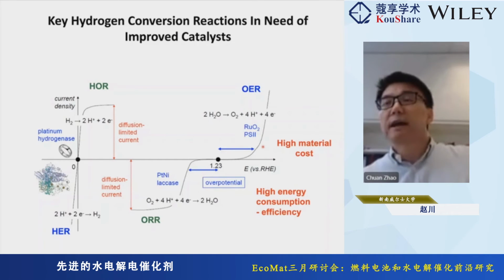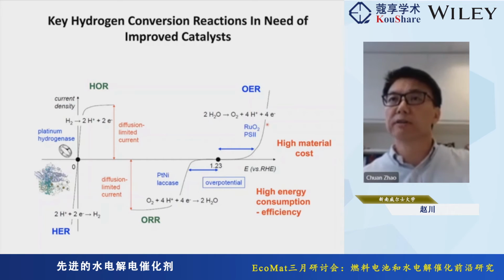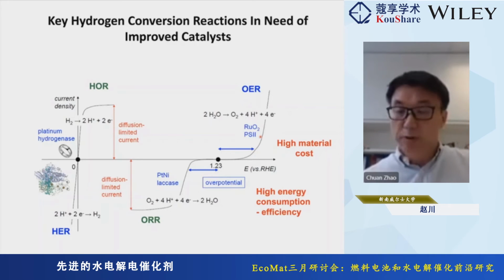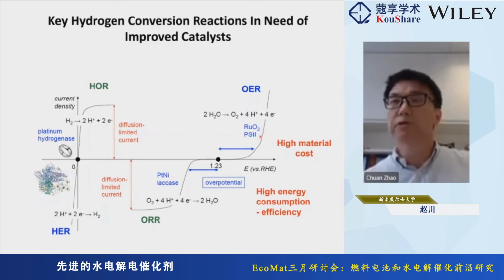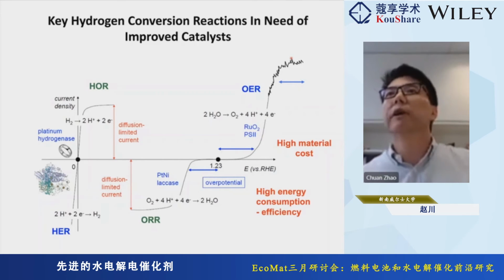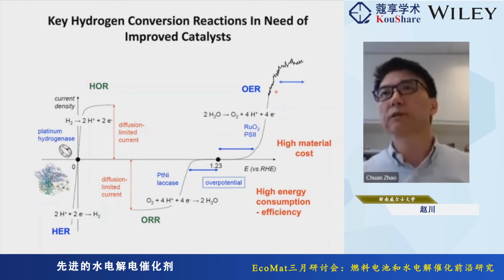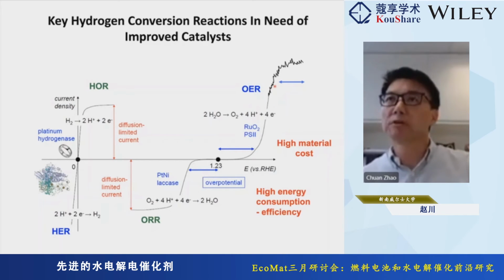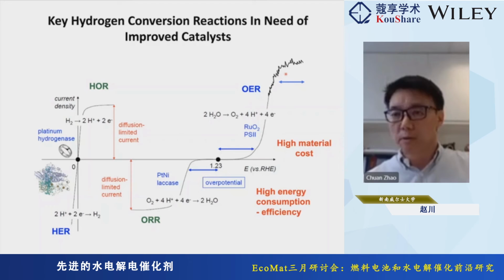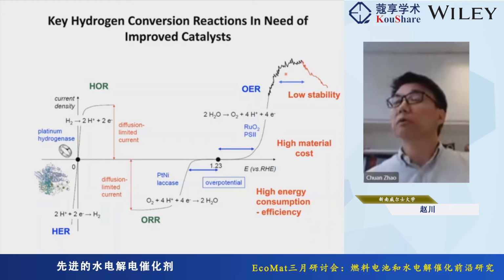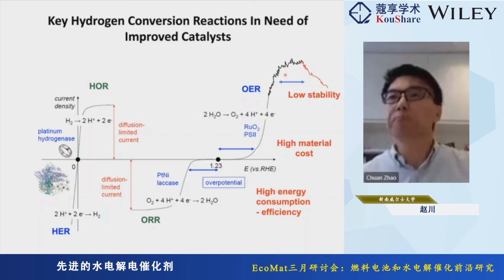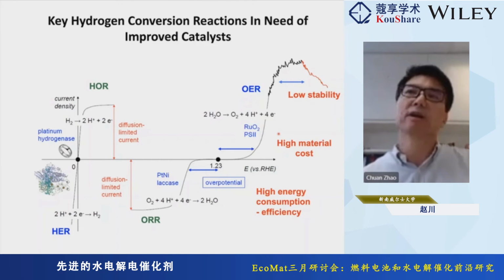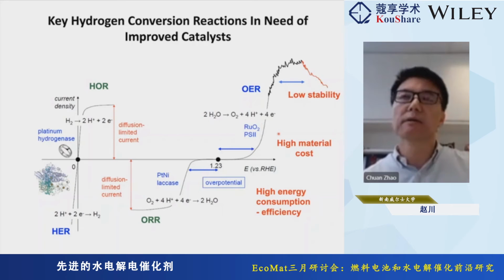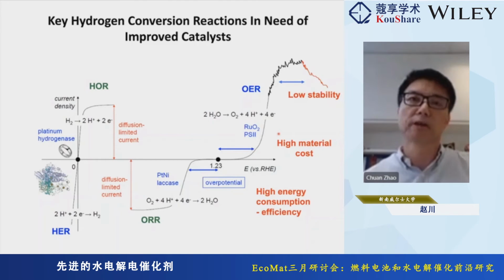And the other issue is, normally we test our catalyst working in this kinetically controlled zone. But in reality, when you really work in the device, you often will step into the mass transport confused area, where we can see a strong gas evolution. Often you will see a very noisy signal, but also you will notice that your catalyst is not that stable. So all these issues are current major hurdles for the electrolysis to produce hydrogen at a low cost.